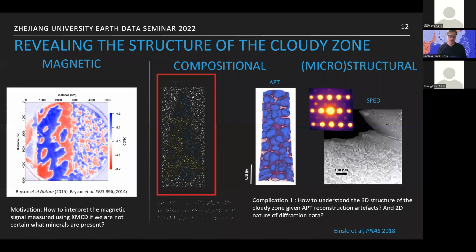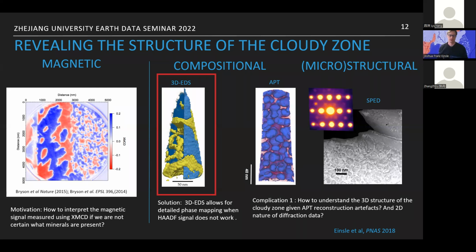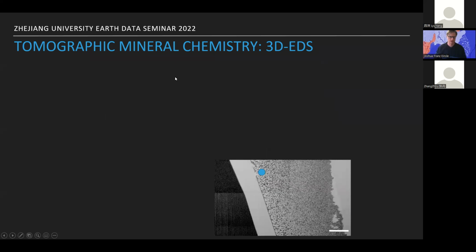And the first answer here was we used a technique called 3-dimensional energy dispersive spectroscopy in a scanning transmission electron microscope. This allowed us to do very accurate phase mapping chemically, especially because there are problems when you try to image this with just the HAADF signal. So to review, for those of you who are not familiar with preparing, this is a polished surface of the cloudy zone. What we would do is use the focused ion beam to lift out and form a cylinder in a needle shape, such that we get a shape like this.